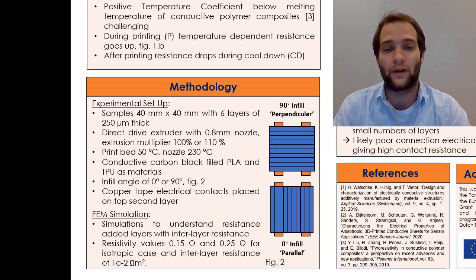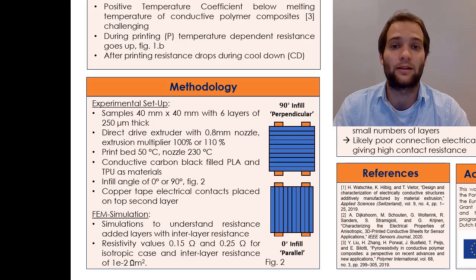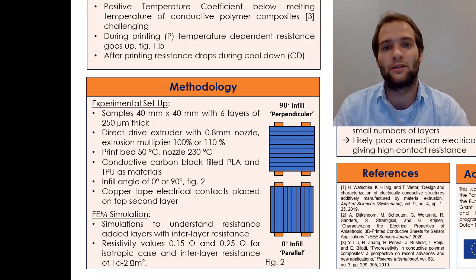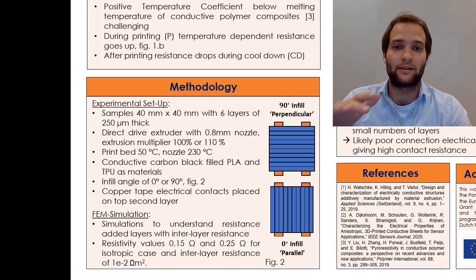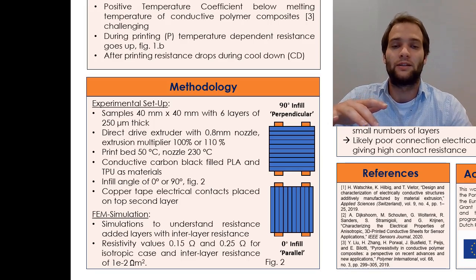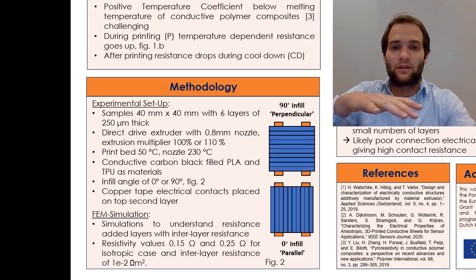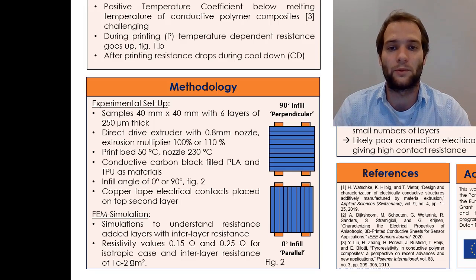Furthermore, we've performed finite element method simulations to better understand the effect of adding layers with both resistivity and the interlayer contact resistance, since with printing the different layers can have a contact resistance depending on the print parameters.